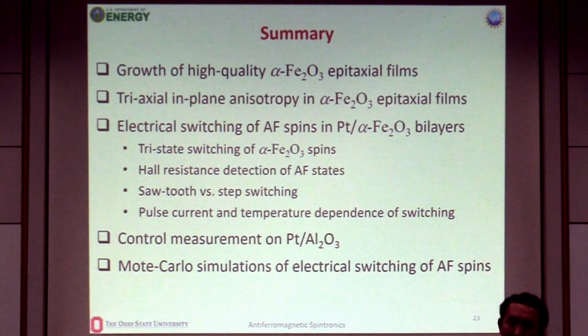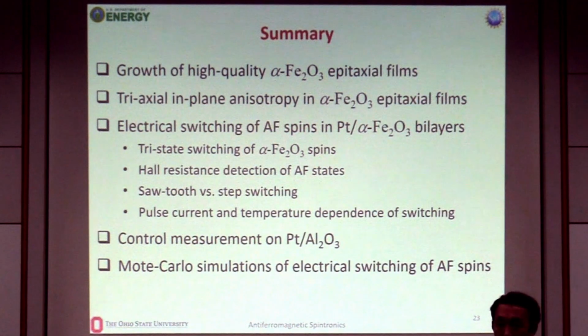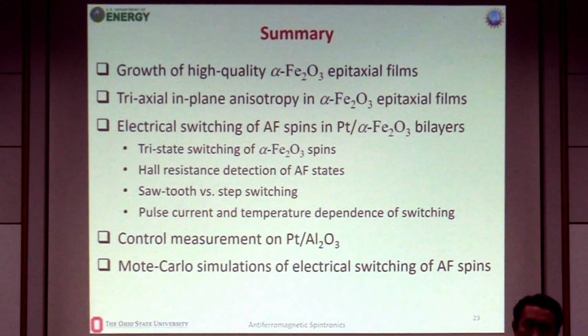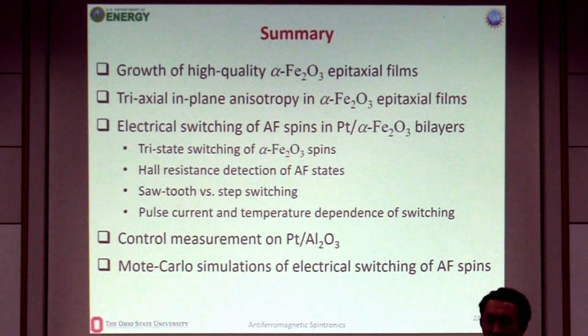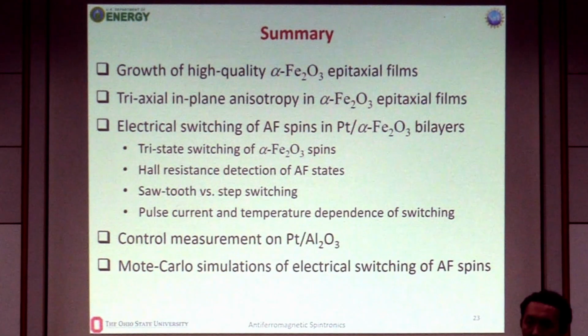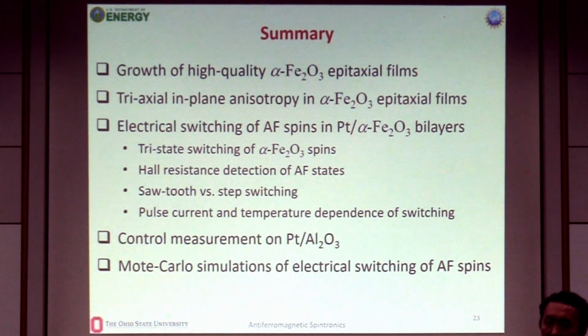You mean, for example, the platinum on sapphire directly? Because of the annealing and the... Yes, it has a history. It's going to decay. The migration is not so repeatable. That's right. So when we do our experiments, we could detect from the cycling property how much of the contribution is from the artifacts. Especially in your experiment, it is measured under zero Tesla, without magnetic field, and 3 Tesla, and there's also some difference. This might also be a contribution from the magnetic structures.